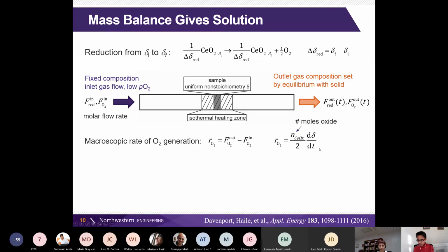So that's straightforward. But now we have a way to write it out and connect that to the change in oxygen content. So if we have some number of moles of material, then the amount of oxygen that's being generated is simply the change in the non-stoichiometry with time. So this is a straight mass balance. And then by definition, the oxygen in is just the partial pressure times the total flow rate going in, so that P is partial pressure, and the coming out is the same thing. It's the amount of flow rate coming out multiplied by the partial pressure of the oxygen in that gas that's coming out.